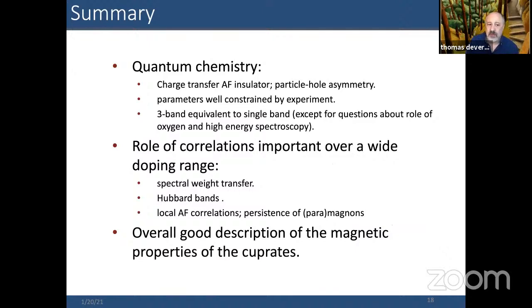Okay. So in terms of this part of the quantum chemistry, I think the behavior of the parent material is very well understood in terms of a charge transfer antiferromagnetic insulator. Comparing with experiments gives us a parameter regime to work with. And there's really no inequivalence one sees in three band versus single band Hubbard models, except if anything, you have a question about the role of oxygen or behavior at high energy spectroscopy like the 6 eV peak and these sort of things. And looking at just doping away from half filling, the role of correlations are certainly important even over a large range of doping in terms of the Hubbard bands and spectral weight transfers and the persistence of local antiferromagnetic correlations, the persistence of these paramagnons. So I would say that this is an overall good description of the magnetic properties of the cuprates.